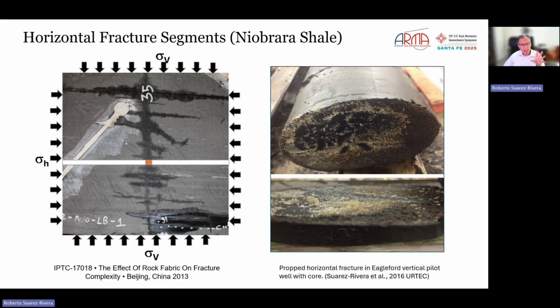And so to test that situation, we ran a test, which is the one I'm showing you, with epoxy. We let the epoxy set for 24 hours before removing the vertical stress and, well, the stresses, and before removing the block. And what we saw is that indeed these features were being created during the hydraulic fracturing process. It was not an artifact of unloading. This was done in 2013.